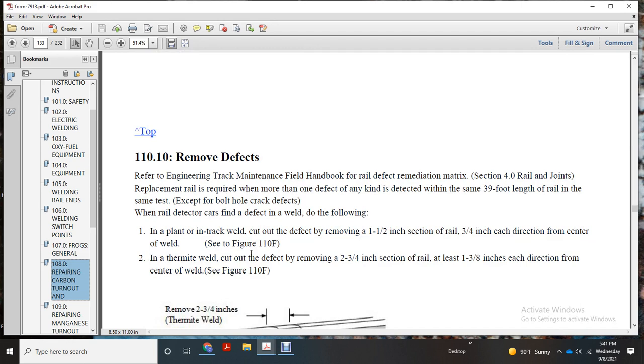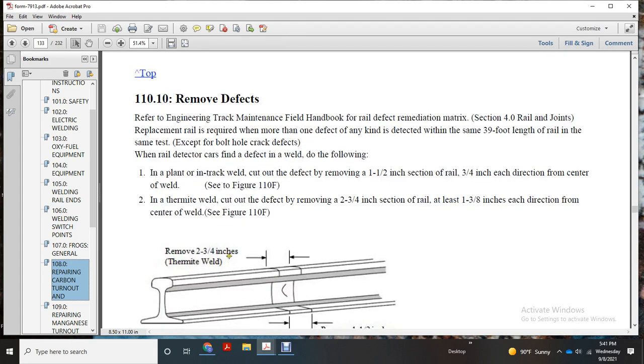If a defect is found within a weld, do the following. For an in-track weld, cut out the defect. Remove a 1 1/2 inch section of the rail, 3/4 inch in each direction from the center of the weld. For a thermite weld, cut out the defect. Remove a 2 3/4 inch section of the rail, at least 1 3/8 inch in each direction from the center of the weld.